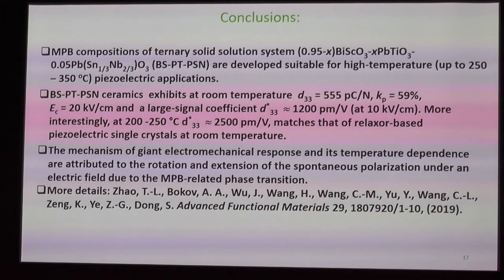Yes, I suspect that what you have as the tetragonal phase is a super tetragonal phase. Bismuth scandate by itself, of course, you cannot synthesize, but if you solve it in the computer with the usual lead titanate structure, it happens to be super tetragonal with a c over a of 1.3. So I suspect that 40% bismuth scandate is super tetragonal.